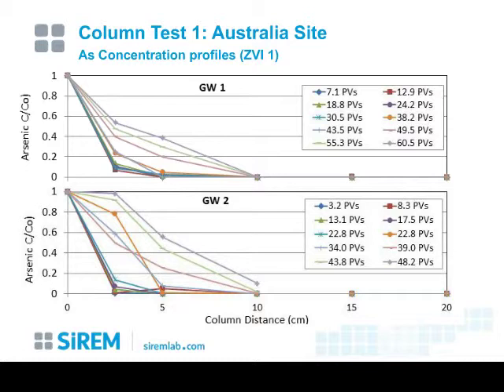And so you can see in groundwater 1, we did 60 pore volumes, and you can see that at this port here that I'm pointing to, at 60 pore volumes, we had breakthrough of the arsenic, whereas at 7 pore volumes, it was much less. And you can see in groundwater 2, we had much better treatment at this first port, however, we did see breakthrough over time. Essentially, in groundwater 2, we had better removals, but no reactivity with time, and we had a lot less pore volumes in groundwater 2. So we had some different results from each one of them, and they were very useful to the ultimate design of what they were going to use in the field.